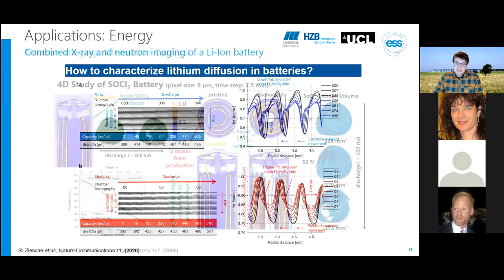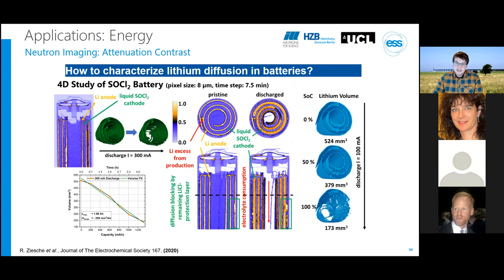Another example by the same research group shows an operating battery during discharging. In this case, tomographies were done every seven and a half minutes to monitor the internal processes in 3D. And on the top left, you see one slice through the center of the battery and how the electrolyte level is changing. You can also see how the lithium diffusion is happening, showing up in yellow. With this example, you not only see nice images now that reveal, for example, production artifacts, but also allow to quantify, for example, the electrolyte consumption.